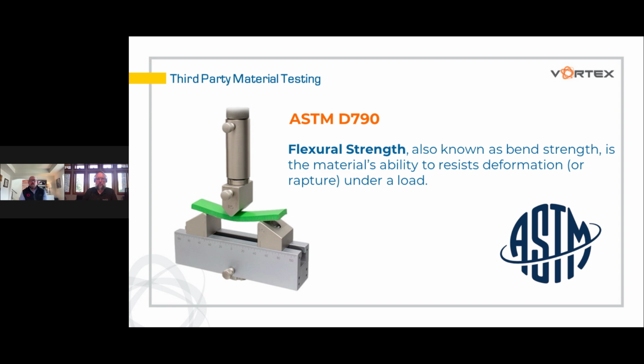So flexural strength is measured using equipment that looks almost exactly like this. What's used is a plate sample, and that plate sample is put between 3 points. Between those 3 points, pressure is put from the top, and you can see in this instance that it starts to bend. So flexural strength, known as the bend strength, is measured by its resistance to deformation. It'll be put under load and sit there for quite a while, but then it'll start to bend.